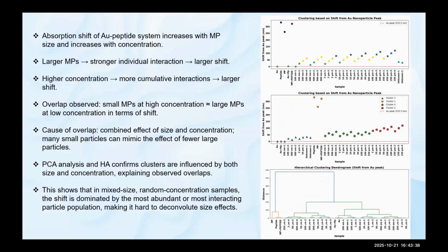Also, we did some data analysis. PCA clustering shows, on the top, based on the color code, the size of the particles at different concentrations. As we go forward, the size increases, and we also have different concentrations for each particle size. We see an increasing trend, but as you see, there is some overlap. For example, smaller particles at higher concentration are similar to bigger particles at lower concentration, because the surface area is very similar. So what matters here is how much surface area is available for the peptide to bind to the microplastic.